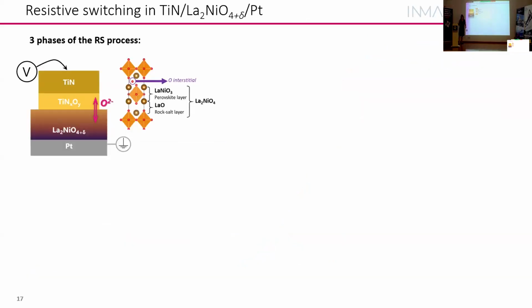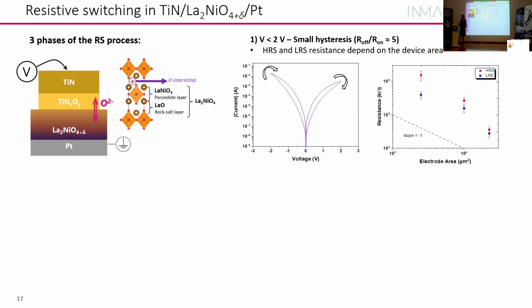Okay, then we try to switch these devices as we want them for resistive switching memories, and we could see that we could play in different regimes. So if we play with a low voltage range, positive and negative, ±2 volts, we can show this relatively small on-off ratio of 5. And if we plot the resistance versus the electrode area, we see that we have a slope of about -1. And this is telling us that it's the whole area that's switching. So we have an interface type switching in this case.